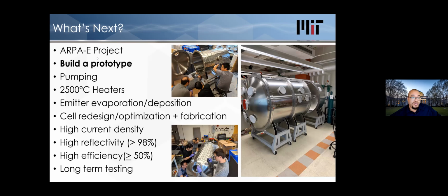So where are we at now? We have an ARPA-E project that's underway. We're trying to build a prototype where we've actually demonstrated, we're on record with the Guinness Book having done 1400 C. We've actually pumped silicon at 2000 C already. So we've broken that record. We've got to apply for the new record. We've demonstrated running our heaters up to about 2500 C. We're trying to deal with an issue of emitter evaporation and deposition.